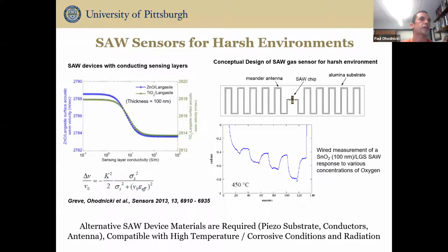These devices can also be used at very high temperatures. So this is a field where it's again newer and emerging for this class of devices. There are some established faculty, particularly up at University of Maine, that have demonstrated temperature sensing up to 1,000 degrees Celsius, for example. In the area of chemical sensing, the current limit is about 500 degrees Celsius. And this is an example publication from back in 2013 where we were looking at integrating metal oxides onto the device to be sensitive to oxygen for combustion applications.